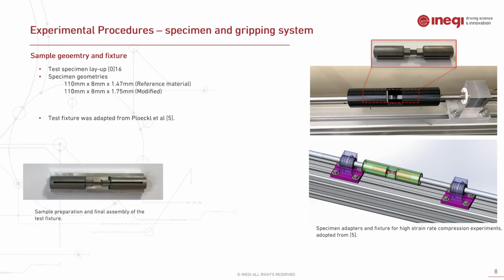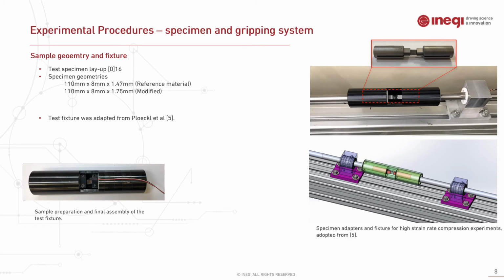Basically, we have our flat rectangular test coupon, which was glued into these two steel adapters. We use a special setup to make sure that the specimen is perfectly aligned. And the assembly was then cured based on the instructions of the supplier, and then we had two mechanical clampings and bonded with the strain gauge to directly monitor the strain value. Then we add the Teflon bushings and the steel tube to prevent misalignment.